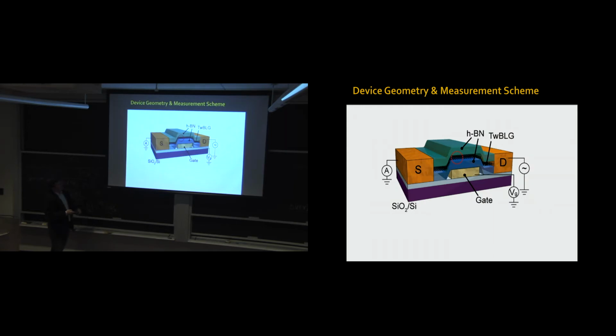So we end up fabricating by picking up another graphene and a hexagonal boron nitride flake such that we end up with this twisted bilayer graphene, which has a bottom and top hexagonal boron nitride, so we have a nice clean sandwich. We contact them with source and drain electrodes so we can apply a voltage and measure a current.